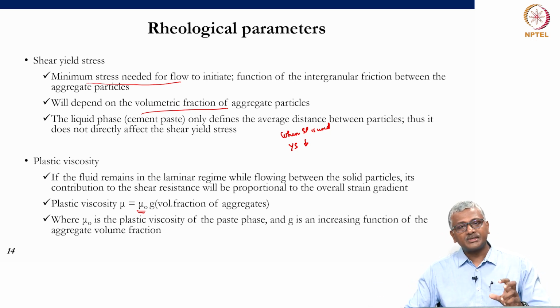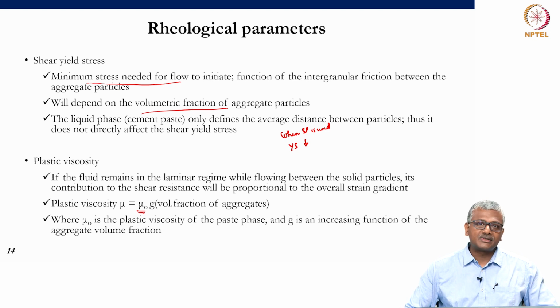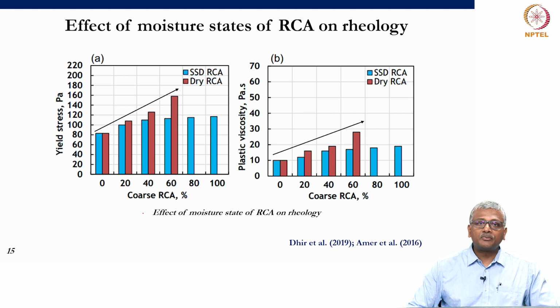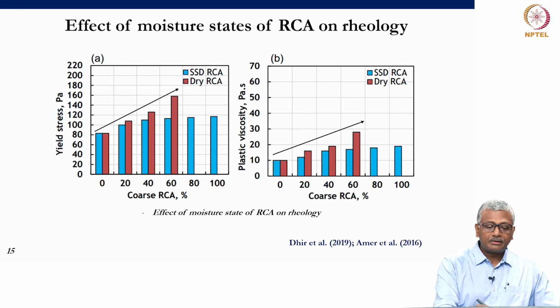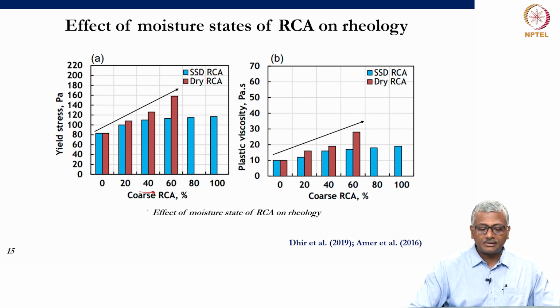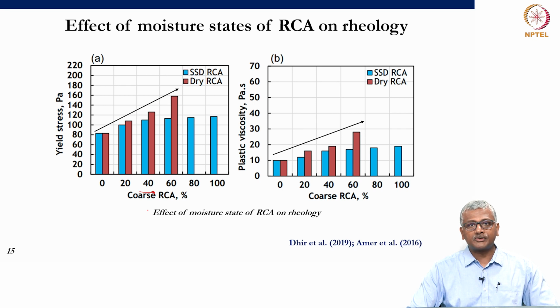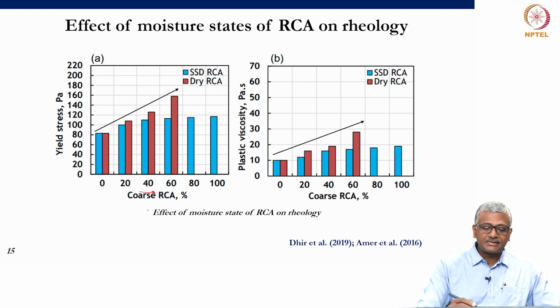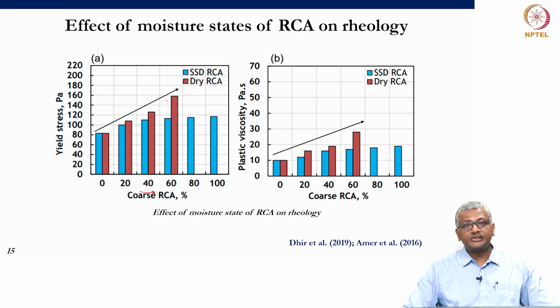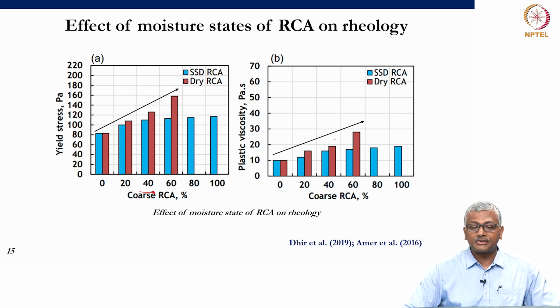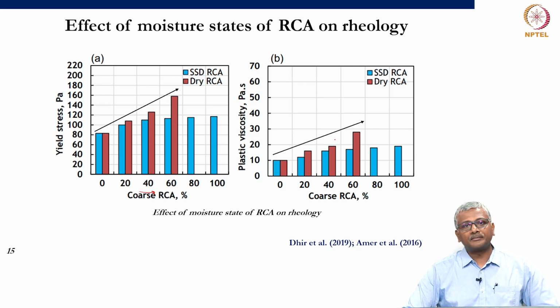What we would like to see now is, what does recycled aggregate do in the system? Okay, when we replace conventional aggregate with recycled aggregate, does it affect our rheological parameters or not? And to this effect, there have been studies done by several researchers which show the increase in the content of recycled aggregate, right. For instance, here on the x-axis what is plotted is the amount of recycled concrete aggregate as a function of the total aggregate. As it increases, you have an increase in your yield stress and you also have an increase in your plastic viscosity. Now, why is this happening?